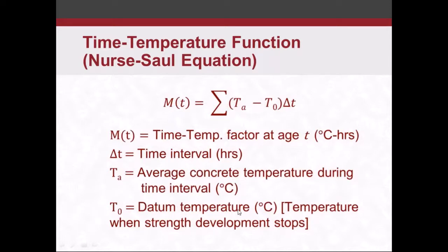T sub 0 is the datum temperature, which is essentially the temperature when strength development stops. There's different ways you can figure this out. The ASTM gives you a way to figure it out using 2x2 cubes, 2-inch by 2-inch cubes, just with cement and water, and then you break those cubes. A lot of people, and the ASTM allows for this, just use a set temperature, 34, 35, 36 degrees, something like that, because we know that's about when strength development stops or gets really close to stopping. So that datum temperature a lot of times is 34, 35 degrees. But this is the equation. Again, it's just a summation of all of the different time intervals and the temperatures.